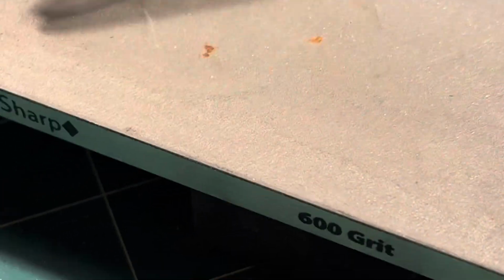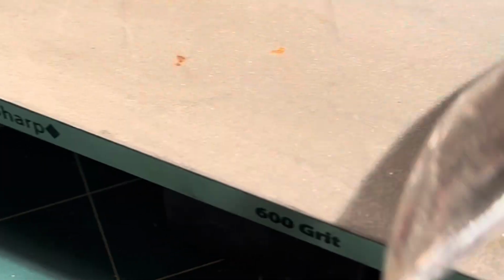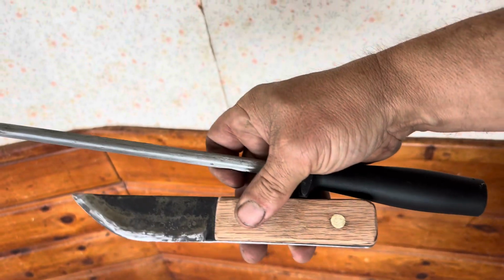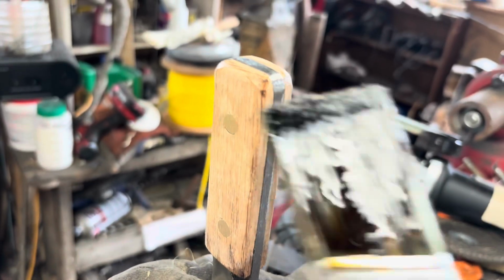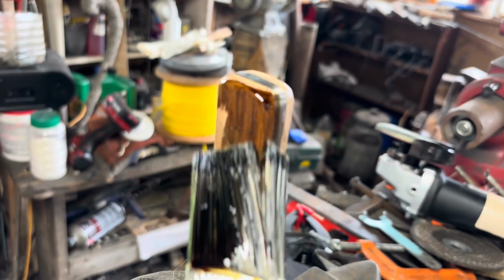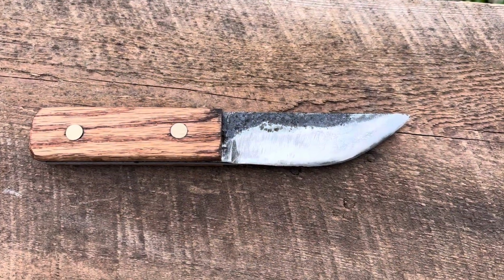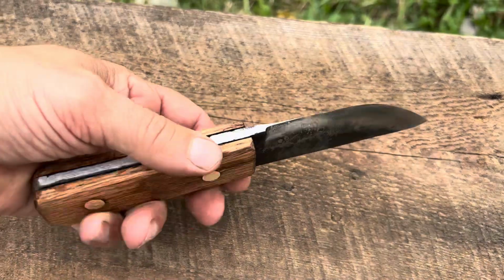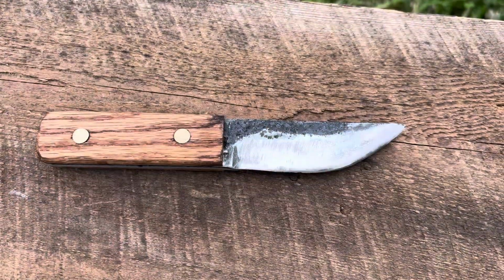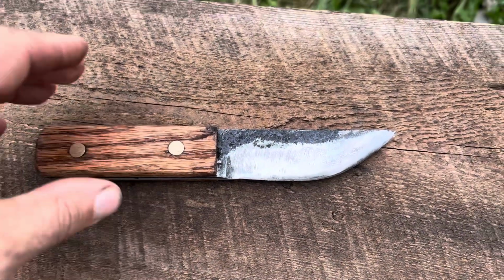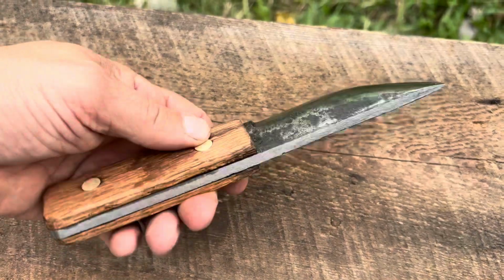handle. This is a bushcraft knife, so it's going to have a convex grind and a 25-degree angle. I sharpened it with 600 grit, and then I took the burr off with a kitchen honing steel. I'm coating the handle with Danish oil for a nice traditional finish, and it's done. It took exactly 3 hours of work, and that's not including the time where I'm waiting for the Danish oil to dry or the oven to temper it.